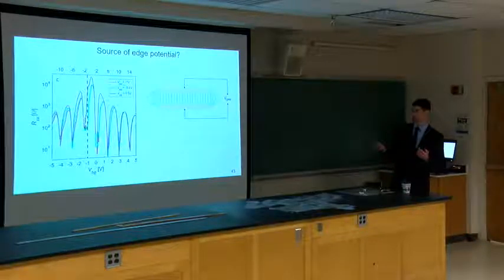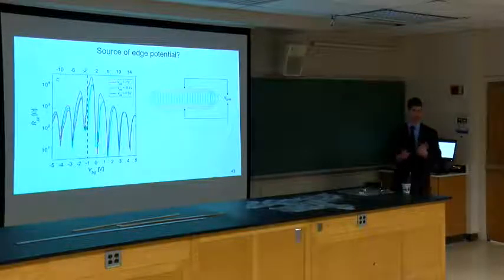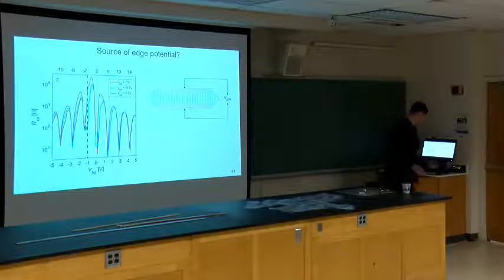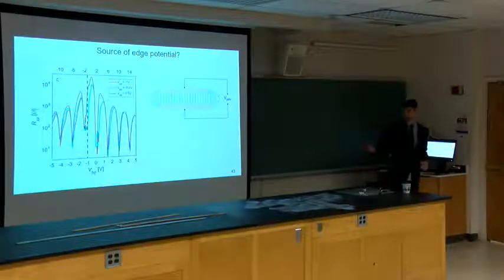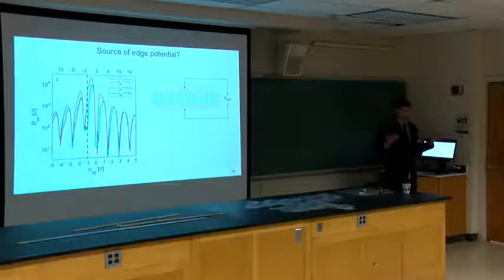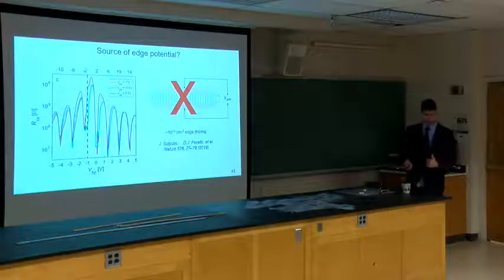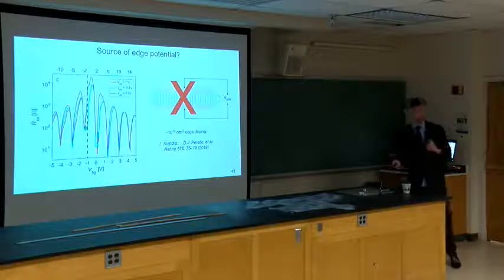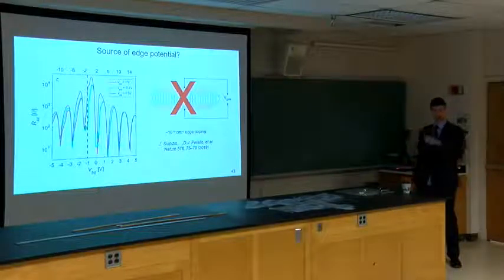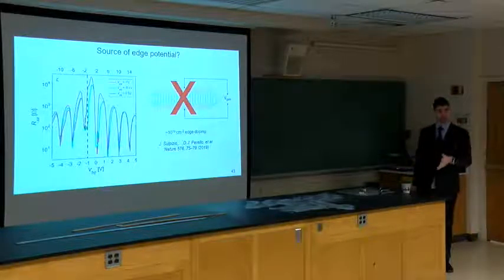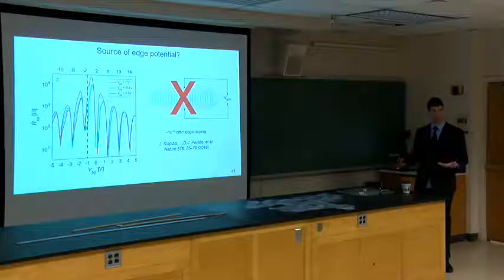Well, if we're changing the plunger gates in our system, we don't see a symmetric effect with respect to gate voltage. Because in this case, if you flip the polarity, the effect should be symmetric, right? I mean, you're just flipping which charge it is. It's not. So what it tells us is that every graphene edge is essentially doped. And the fun thing is that it's actually not dependent on whether you etch or not etch, because one of the edges in the previous device that I showed, and I didn't even have to point it out, was not etched. It was just an exfoliated edge, which should be clean. So it's never seen polymers, it's never seen anything.